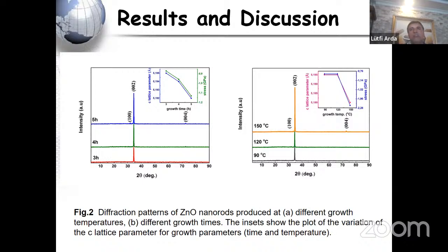In the XRD spectrum of the zinc oxide nanorod, you can see only 3 peaks. They are the 100 peak, the 002 peak, and the 004 peak, and their positions correspond to a typical zinc oxide wurtzite crystal structure. There is no secondary peak. That means there is only the zinc oxide structure, and the sharp peak is the 002 peak.